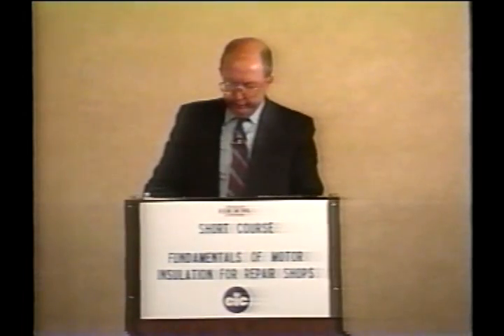For many years, many thousands of machines were successfully wound with machines using the dip and bake process. And that system is still used today in a great many applications, although it certainly is not state-of-the-art, and it is rapidly being replaced with vacuum pressure impregnation or other processes and system treatments in order to develop the superior systems that these technologies and materials make available. Now, a key objective of the makers of a modern insulation system is to produce a void-free system. And void-free is especially necessary for high voltage applications because deterioration of the insulation due to internal corona is a very serious failure mechanism to be reckoned with.